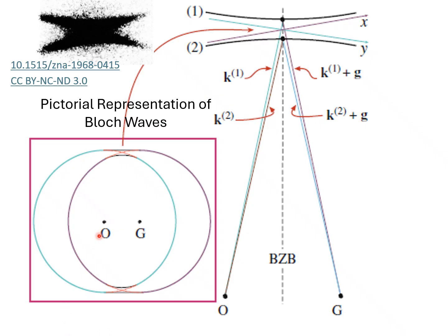And then when they work through the formulations, it turns out that they have to have two solutions to the wave equations, or multiple solutions, two solutions for the direct beam and two solutions for the diffracted beam, which is exactly this. But that's what one would come up with anyway if one simply did a thought experiment and said, what do we have if our wave coming into the crystal is refracted, but it's refracted into two parts?